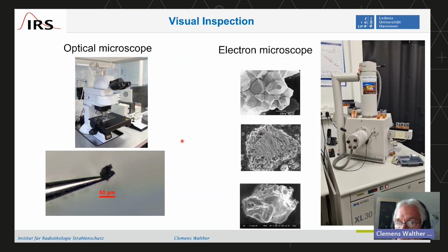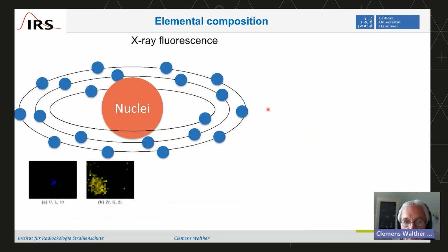What you can do with an electron microscope, and here you see some particles that are radioactive, and these particles are characterized well on the microscale, and you can see at first glance that they differ very much in the kind of structure, and also the kind of structure you find is characteristic for the material.